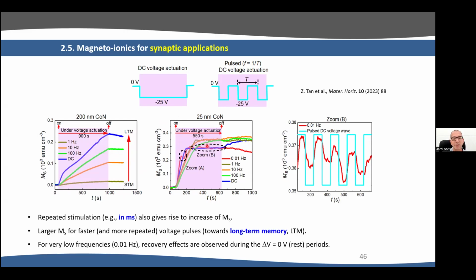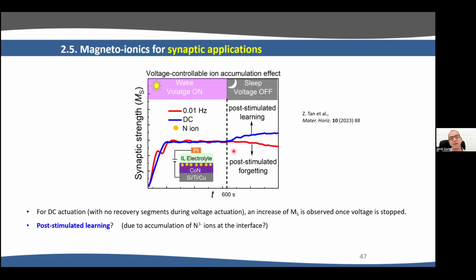Now, if we go to the 25 nanometers film, there is an interesting effect that we were not expecting to see, but it's here. And actually, the effect is comparing these blue and red curves. So if we go very slowly, you can see these oscillations because of the cycles of the voltage gating. We induce and we suppress like this. If we apply the same, what happens is that when we stop the voltage, the magnetization continues to increase. So actually, it's shown better here.